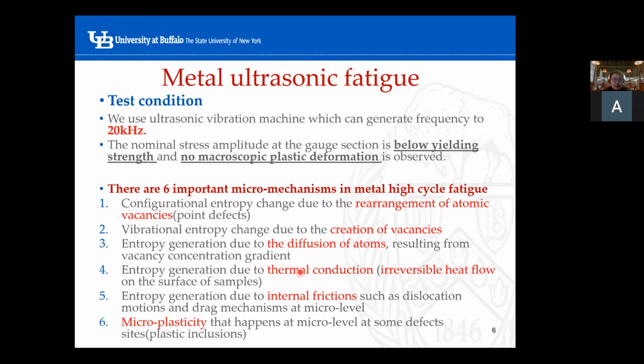Among these 6 mechanisms, the entropy generation due to thermal conduction, internal friction, and microplasticity will be strongly affected by frequency. Thermal entropy generation due to thermal conduction, when we apply ultrasonic vibration to the samples, will have a larger temperature increment compared to conventional high cycle fatigue.